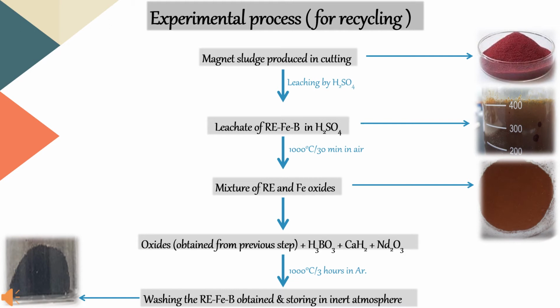Re are the rare earth elements, and the Re in this leachate is actually a mixture of different rare earth elements. By ICP analysis, we find that it is a mixture of Nd, Dy, Tb, and Gd. All the commercial NdFeB magnets use different kinds of rare earth elements. Gd increases the Curie temperature, and Tb and Dy increase the anisotropy energy, BH-max, and MR value.